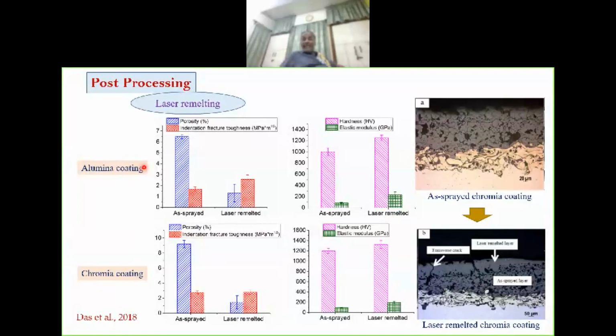Okay, but the remelted layer must not be too thick. During contraction, we are getting a melt pool. If it contracts, if it's too thick, there's a chance it will come off. So a scope of optimization is there. But one can improve the property with this type of post-processing.